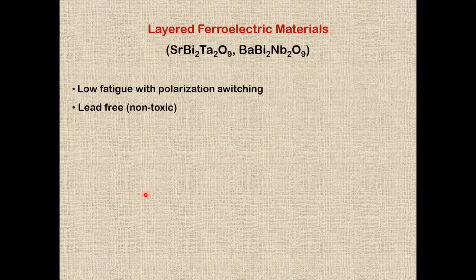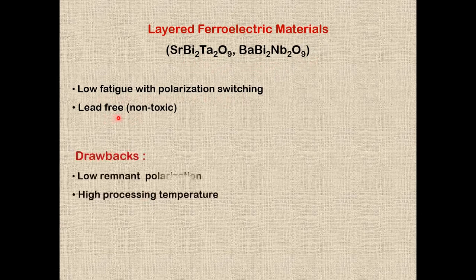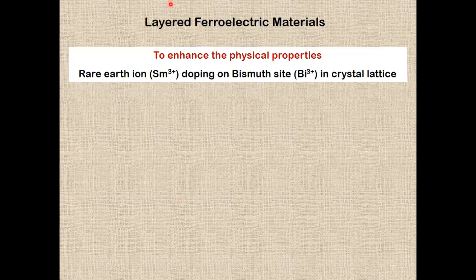Renewed interest stems from layered ferroelectric materials such as strontium bismuth tantalate (SBT) and barium bismuth niobate (BBN) due to low fatigue with polarization switching and also because they are lead-free. However, these compounds do have drawbacks: low remnant polarization and high processing temperature. The most effective approach found in our research to enhance their physical properties is by doping rare earth ions on the bismuth site in the crystal lattice.